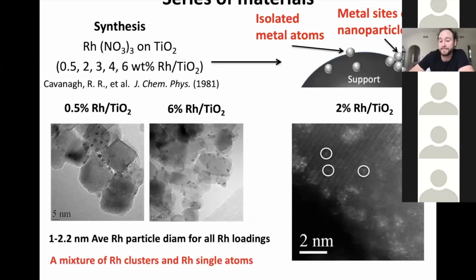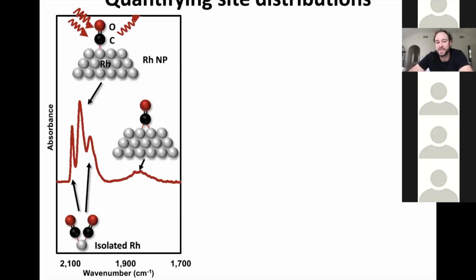So if you did aberration corrected TEM, and I'll show you much nicer images later, we definitely saw on all of our samples some clusters, some single atoms, telling us that we have some picture that might look something resembling this, but we needed a better way to quantify this. So the way that we went and tried to develop a quantification of these site distributions is the following.